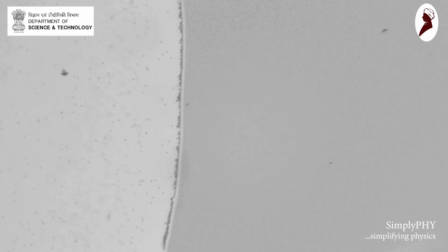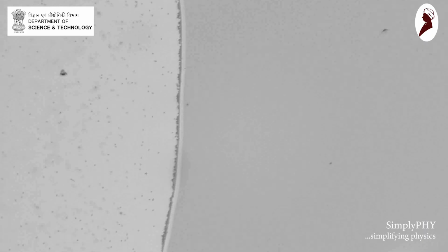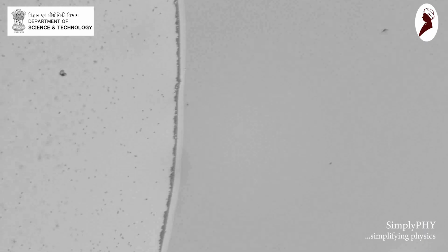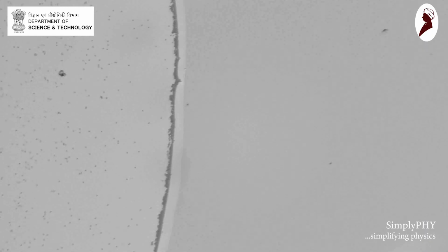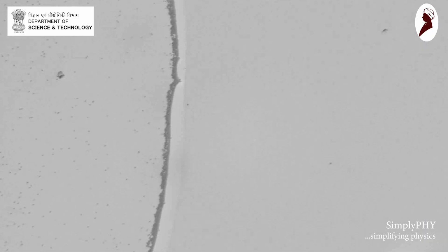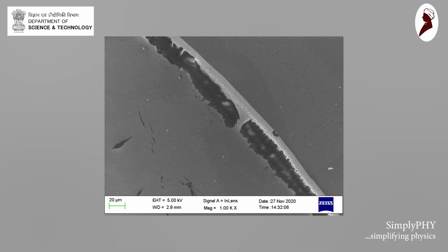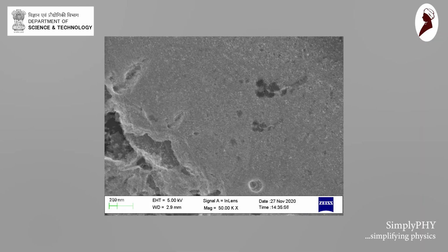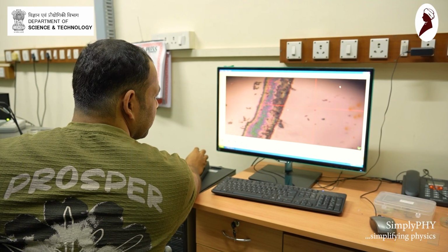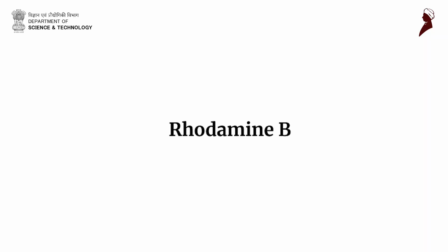As the evaporation proceeds, more gold particles deposit at the edge of the droplet due to a balance between repulsive electrostatic force and attractive van der Waals and dipolar forces between the nanorods. These particles self-assemble and form a highly ordered structure. This immediately became interesting for surface enhanced Raman spectroscopy for detecting minuscule amounts of any substance using a metallic surface like gold or silver. We set out to test the limits of detection using this technique, focusing on rhodamine B.